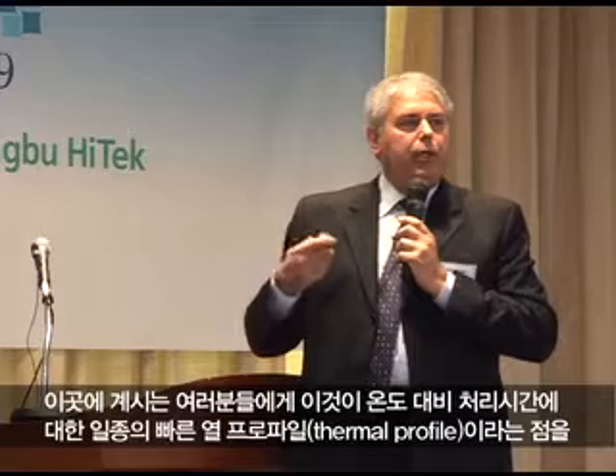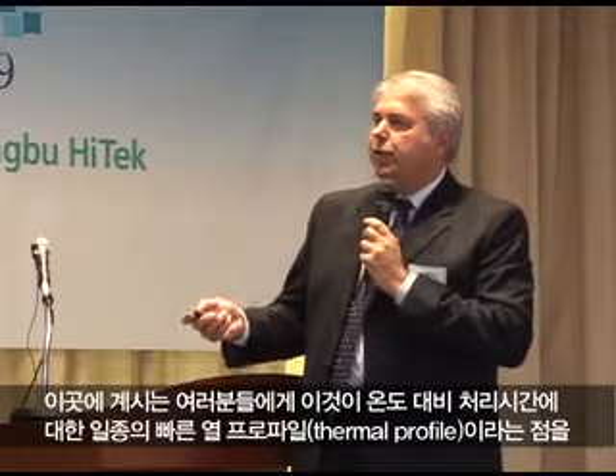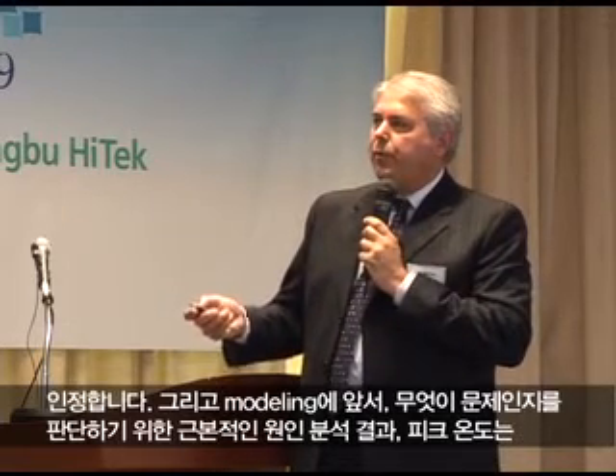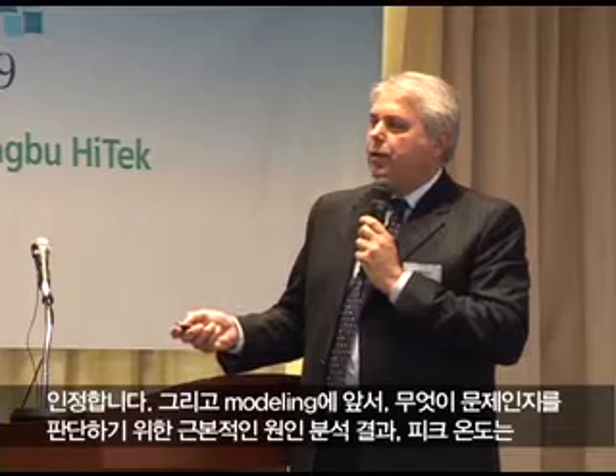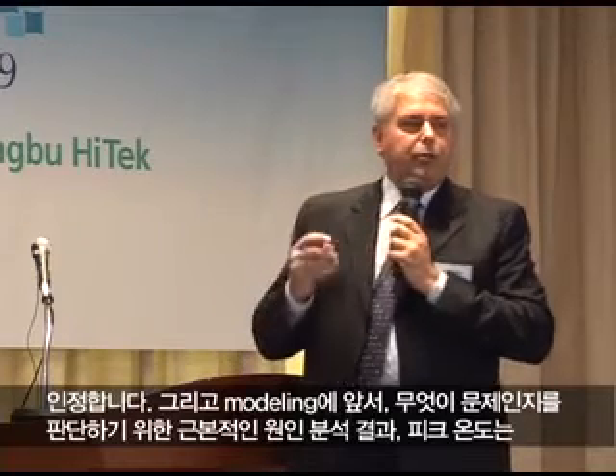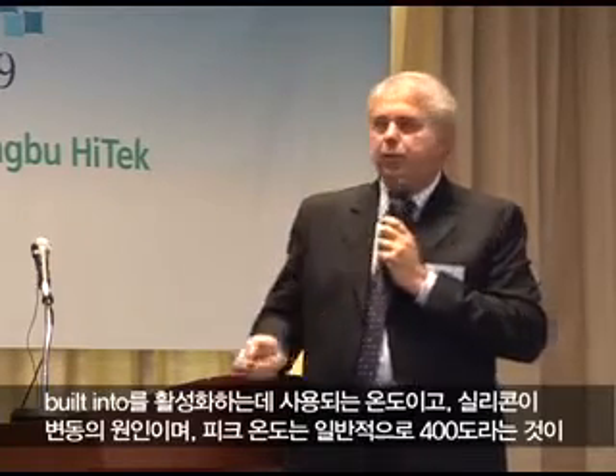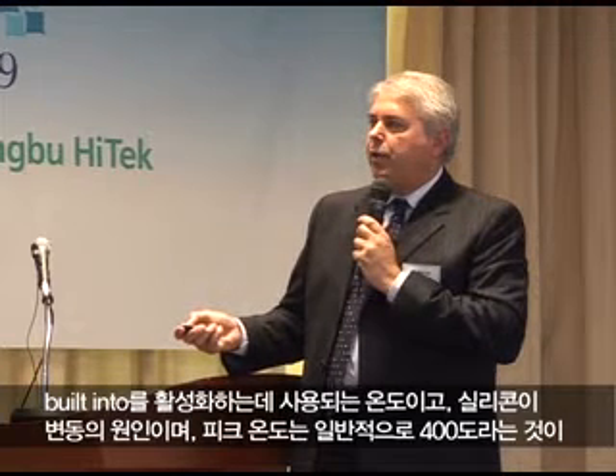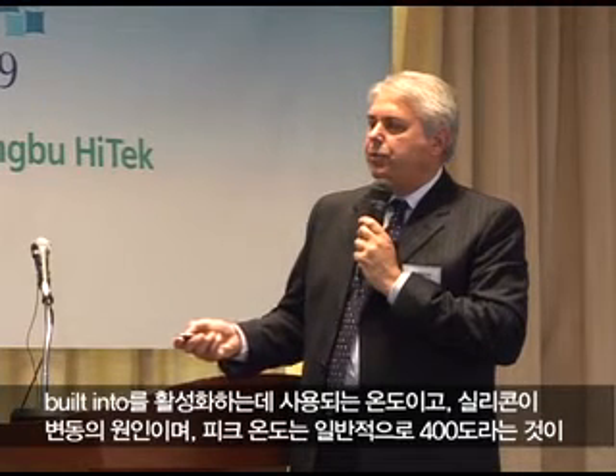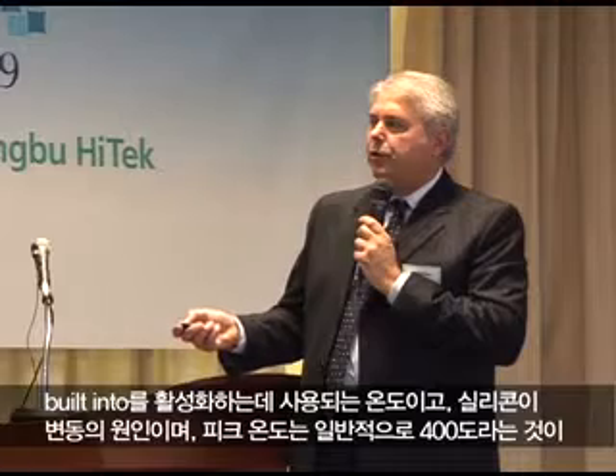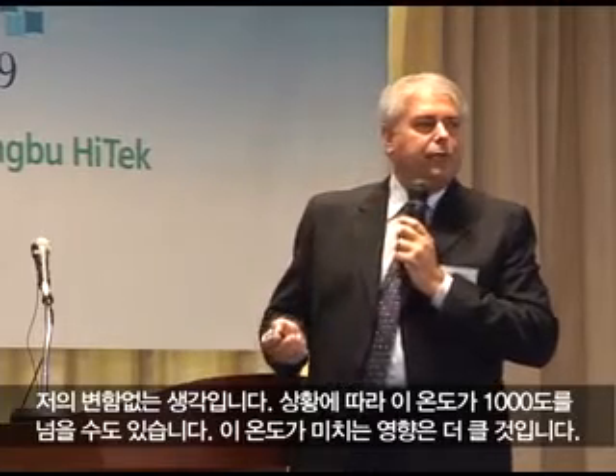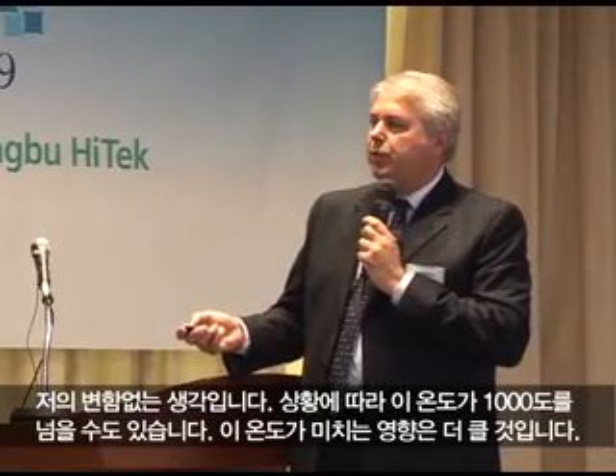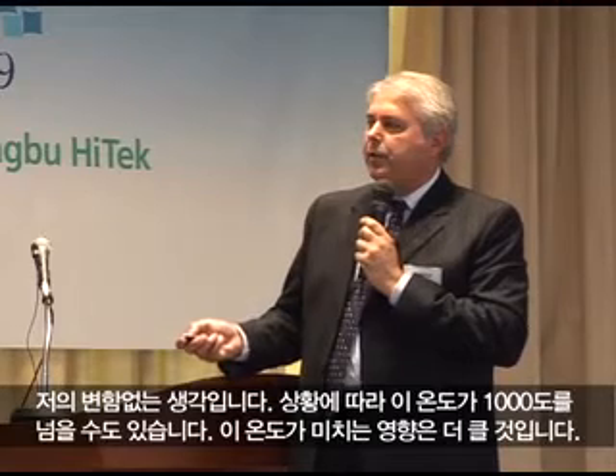And in going through the root cause analysis, or let's say in trying to understand what was the problem before modeling, it's always thought that the peak temperature, which is the temperature that's used to activate the dopants in the silicon, would be the source of the variation, because this is maybe typically 400 degrees and this might be over 1,000 degrees. And so this one is always thought to have the higher impact.